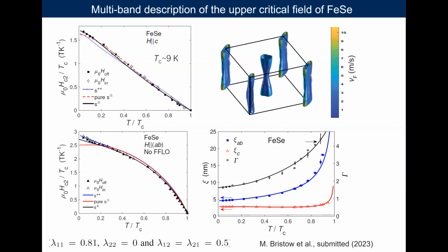That's right. I would encourage this type of calculation to be done starting from the band structure and really accounting for everything. What we took from the literature is an existing model by Gurevich, which I think was developed for a multiband, probably three-dimensional Fermi surface. And we just tried to understand which parameters would be suitable to describe both orientations with the same type of parameters. And obviously, this gives you information about the Fermi velocity anisotropies. But in reality, if we want to be very precise, it would be great to have the precise Fermi surface included in the model.